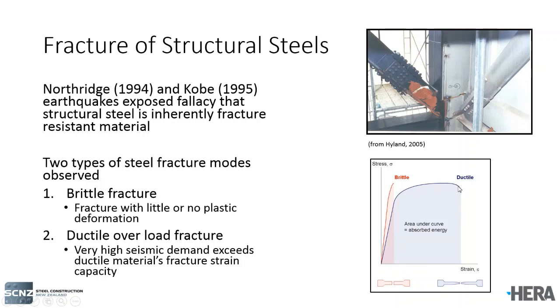And so the second type of fracture mode that was observed in those earthquakes was what's called ductile overload fracture, which, as the name suggests, the behaviour was actually very ductile. What happened, though, was that the seismic demand was so high that it actually exceeded the fracture strain capacity, so we ended up somewhere out here in the steel.